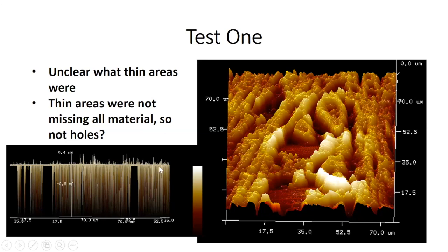Because the sample was grounded and a minus 10 volt bias was applied to the probe, the only currents that should have been measured would have been negative or flowing out of the node, out of the probe into the ground plane. This is using the convention that the direction of electron flow out of a node is negative current. Because the probe has a negative voltage, it is an electron source and should have only created negative currents into the ground plane. These positive currents represent electrons flowing into the probe against the minus 10 volt bias voltage, which would require a more negative potential to create. This is unusual and non-classical behavior.